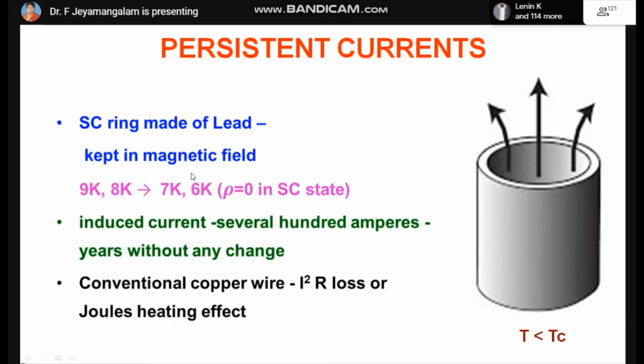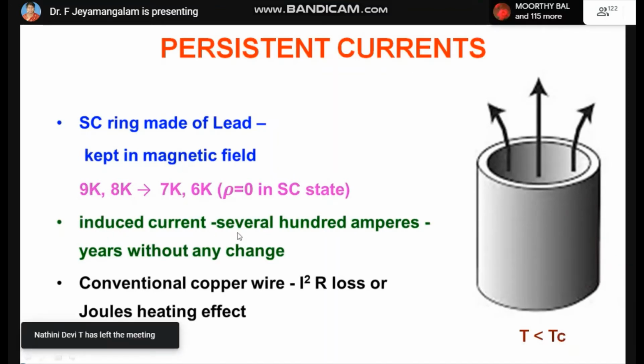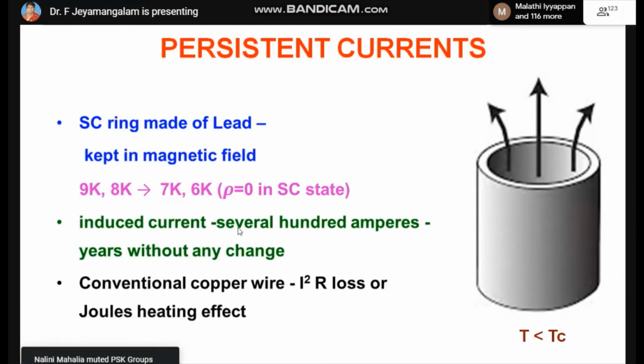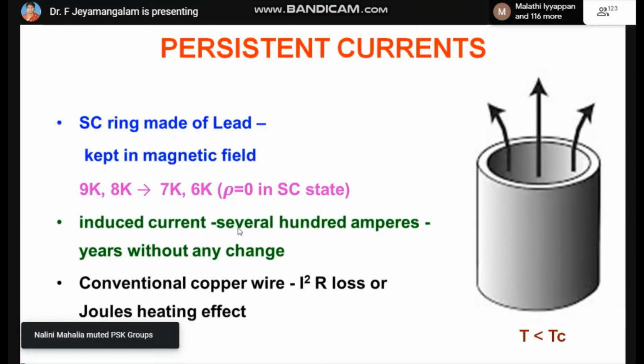So when the temperature is reduced, the material is getting transformed from normal to superconducting state. In that case, there will be a change in the magnetic flux lines. When the flux lines are changing, current is induced. The induced current will run for several years without any attenuation. It can be a few amperes or a few hundred amperes. In one particular experiment, the induced current was flowing for years together without any attenuation or decrease.